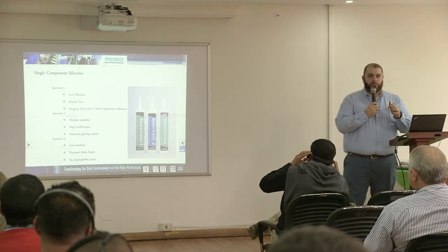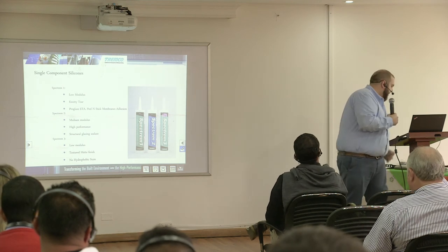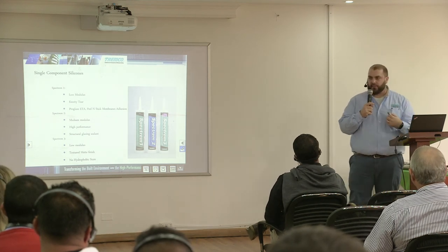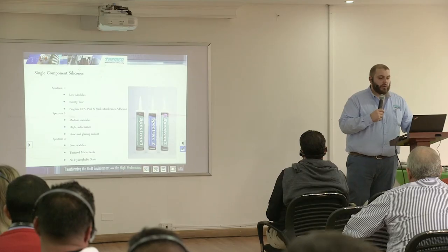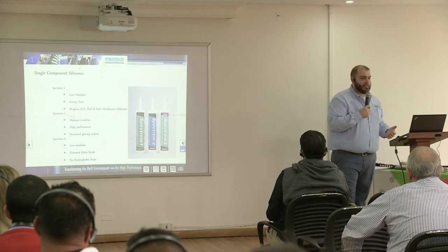The cool part about using our Spectrum 1 is if you poke a hole in it, I don't have a knife on me, but I can show you guys after the fact or at the break if you want to come up here and see it, that hole will not propagate. If you use some of our other silicones or even competitor silicones and you puncture a hole, the hole in the silicone sealant will propagate and unzipper down the joint. The benefit of not having that joint unzipper is you only have to replace a smaller section of the joint, 6 inches on both sides of that penetration, that tear. It's quite a unique feature comparatively to other silicone technology.